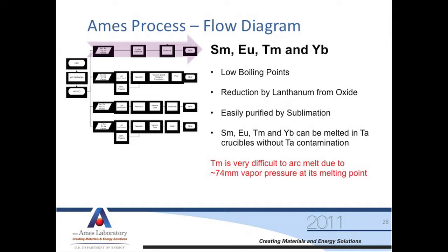Thulium, for example, has a vapor pressure of 74 millimeters at its melting point. To give you a reference, atmospheric pressure is 760 millimeters. So it's almost a tenth of an atmosphere. If we tried to arc cast it, we'd lose 50% of the metal. It would boil off.